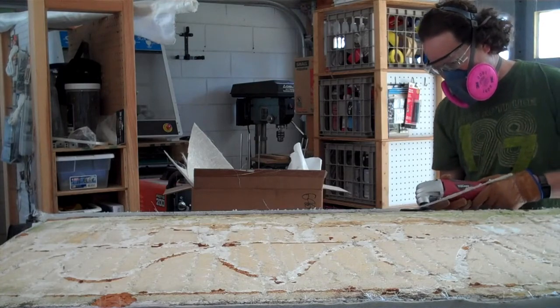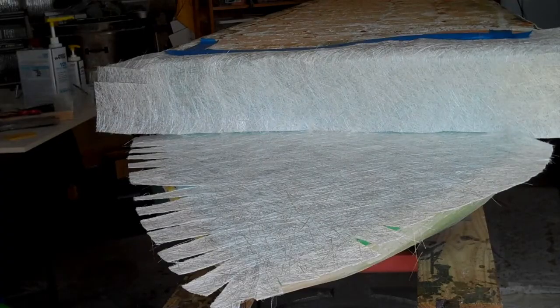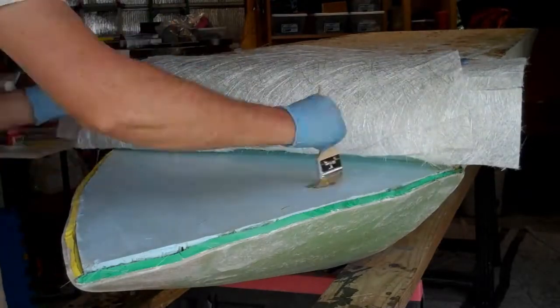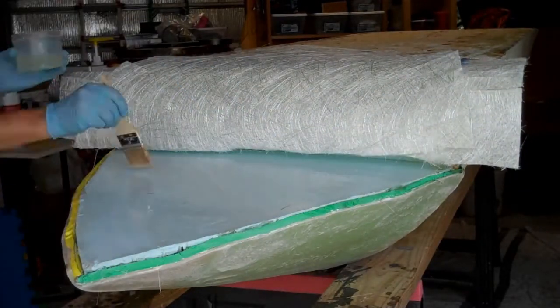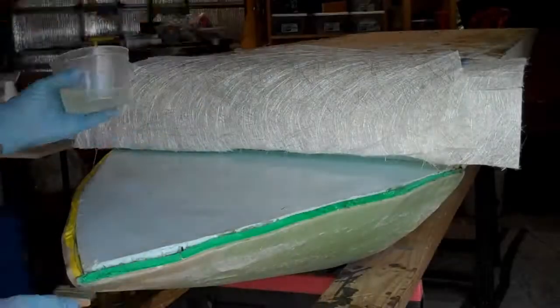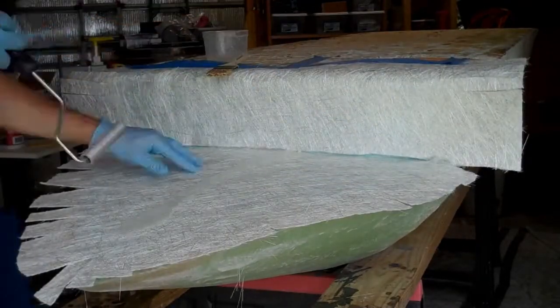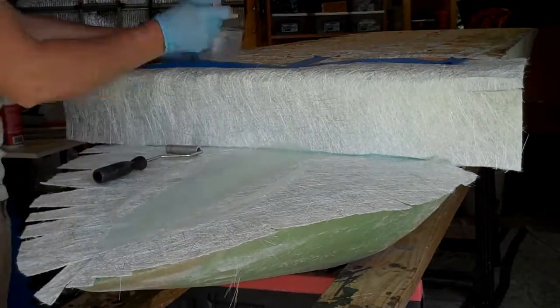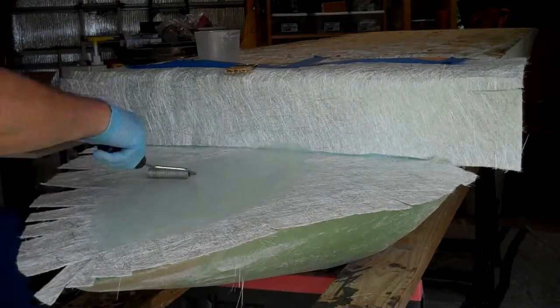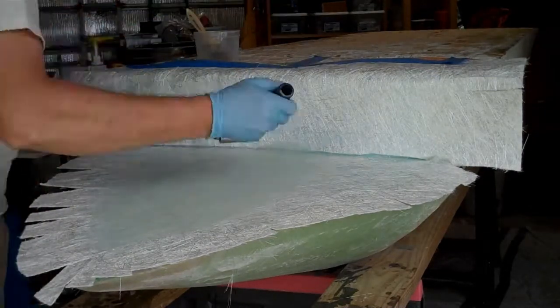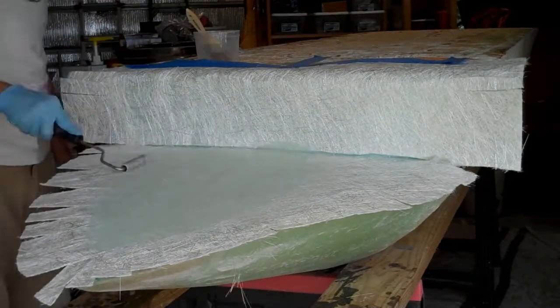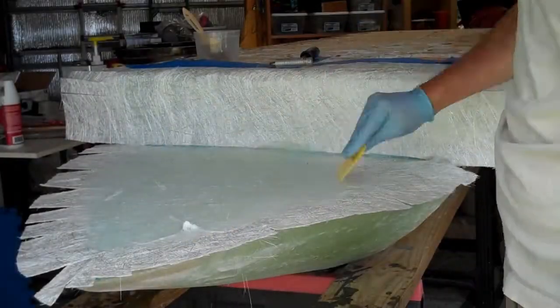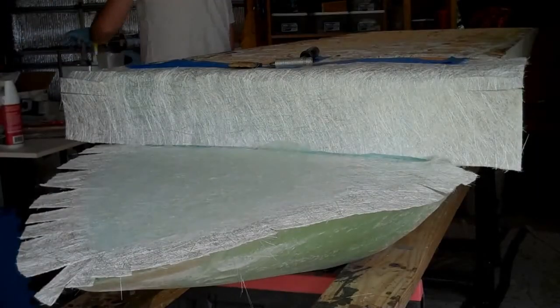I cut out more chop strand mat for the nose cone. Notice the multiple feathered cuts around the edge, which will allow it to wrap around the edge of the bottom piece. My normal procedure is to paint epoxy onto the foam first to make sure that the foam is fully coated and that the fibers on the very bottom pressed against the foam will get enough resin. Then I liberally apply resin to the top of the chop strand mat and use a plastic spatula and fiberglass roller tool to make sure it gets distributed throughout the entire chop strand mat and into all of the fibers.